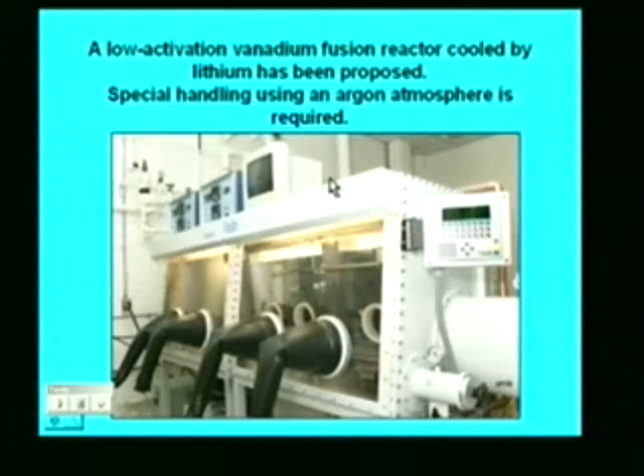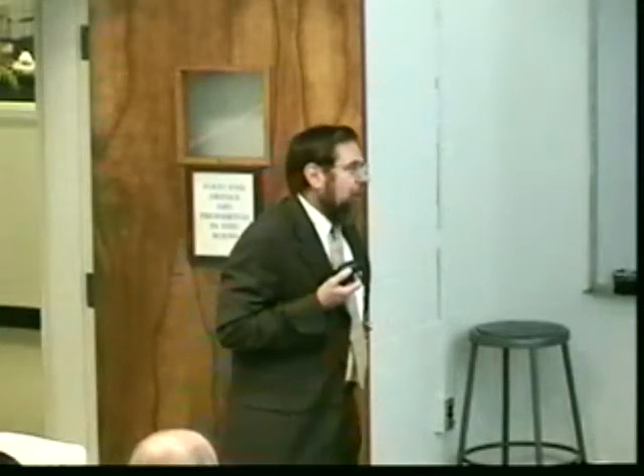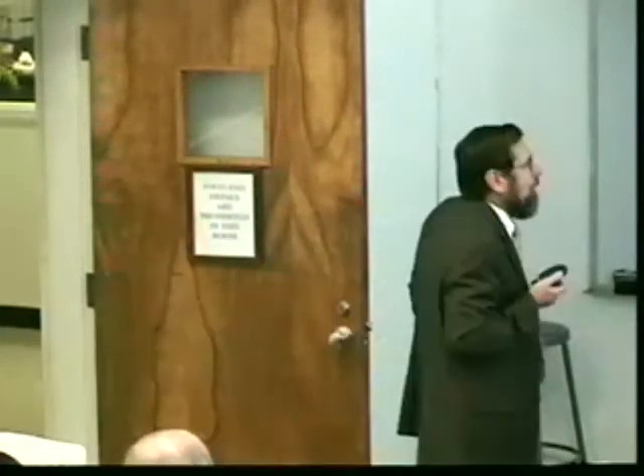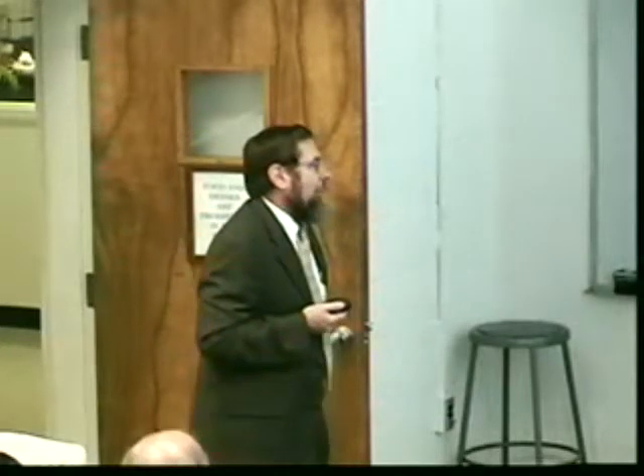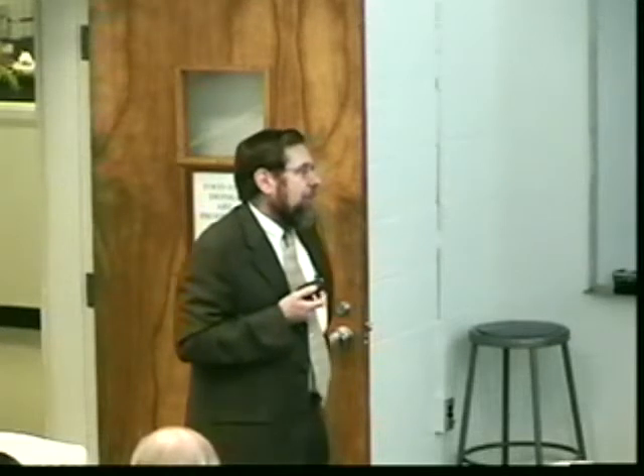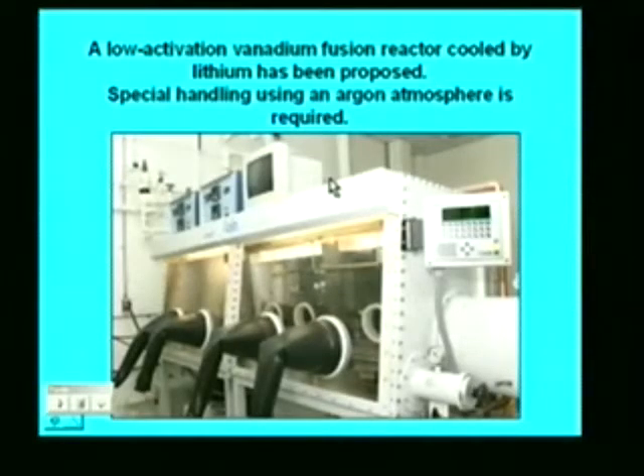And the vanadium system would be cooled by lithium. Two reasons. One is that lithium can be used to generate tritium to fuel the reactor. The other is that lithium is compatible with vanadium as a coolant. Water or gas would not be, because you can't, for example, get helium pure enough to not embrittle the vanadium. In the case of lithium, the primary contaminant is oxygen, and the oxygen will primarily go into the lithium rather than the vanadium. So it's a nice material for vanadium.